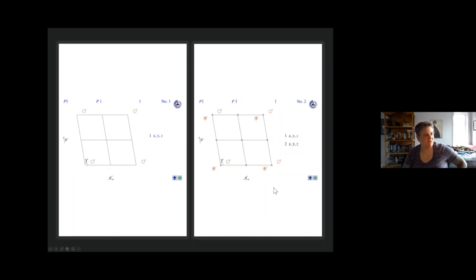So here are the two simplest ones: P1 and P bar 1. That's point group bar 1 and point group 1, both triclinic, and you can see they're very simple symbols. But these elements here tell us about the atoms in the structure. When we're trying to calculate things and look at where atoms are, we have to calculate their actual position based on XYZ in the structure, and we use these symmetry operations to define where we're going to put the elements we're looking at. We have computer programs that we enter this into, and it does that.